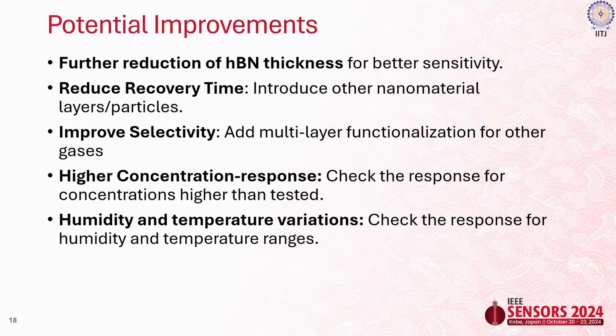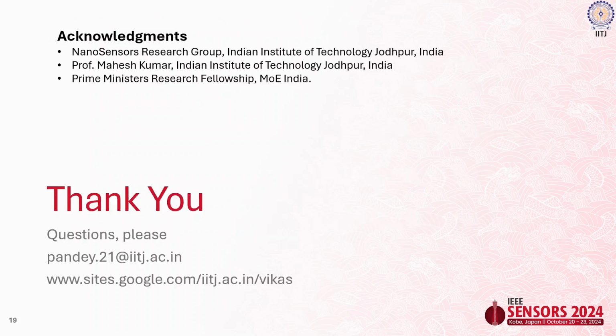The potential improvements that we are presently working on are further reduction of hBN thickness for better sensitivity, since we got only up to 200 nanometers, and reducing recovery time by introducing other nanomaterials like layers or particles over it, and improving selectivity by multi-layer functionalization, and also going for higher concentration responses and checking the humidity and temperature variation. So that's all with my presentation.